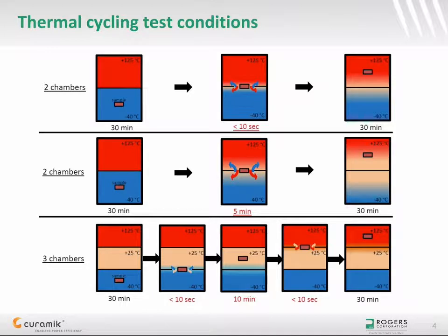The device under test is placed in a climatic chamber at a low temperature for a given duration and then moved in a second climatic chamber at a high temperature for usually the same duration. This represents one cycle, and this cycle is repeated many times till one can observe a first failure up to end of life. While almost every manufacturer of substrates will use the same test method, you should pay attention to the details as the test condition may significantly influence the test results.